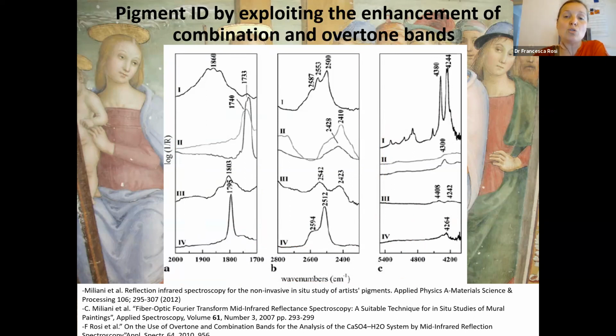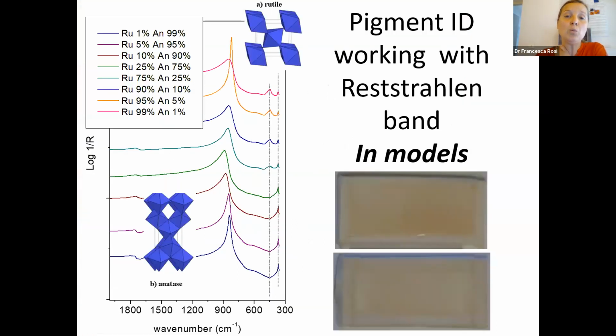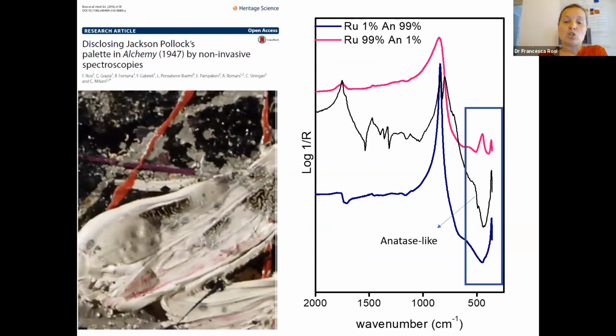And these can be used also for other types of inorganic compounds, including phosphate, sulfate, chromate. All of them have specific combination and overtone bands that can be used for their identification. But we can work also with the Reststrahlen band. Here you see, for example, the reflectance spectra recorded on titanium white models in oil paint, in which we have different proportions of the two polymorphs of titanium dioxide, anatase and rutile. It is possible to exploit these differences also for revealing, for example, the presence of the anatase polymorph in a thick white paint, along with zinc oxide, in the painting Alchemy by Jackson Pollock.